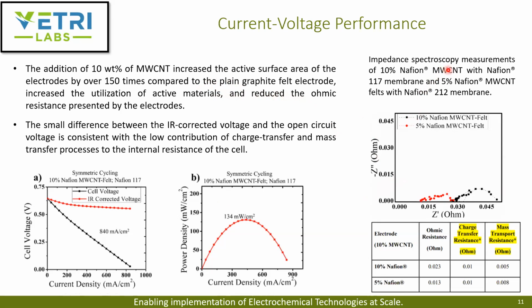they did the impedance spectroscopy for the 10% Nafion on the multi-wall carbon nanotube with graphite felt, and also 5% Nafion. So when they prepare the electrode, they add Nafion as a binder, right? So they played around with the concentration around 10% and 5%. And with the 10%, they used a thicker membrane, which is a Nafion 117. And with the 5%, they used a thinner membrane. So basically, the ideology is to decrease the amount of Nafion. And what they found out was the